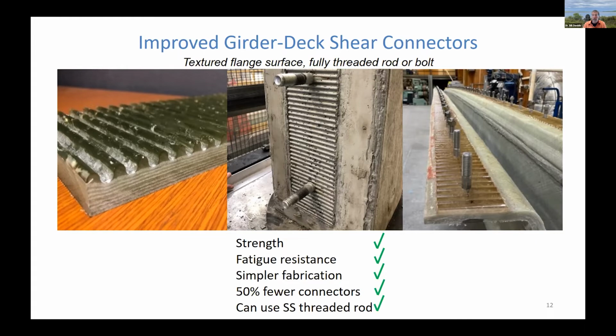And we can also use now, we proved that we can use a stainless steel threaded rod for that connection. So we don't have to worry about keeping threads out of the shear plane. We don't need to worry about using a high fatigue resistance material. We can go with stainless steel. It's 100% corrosion free. Much simpler to fabricate because not only do you have half as many holes, but those holes do not need to be tightly toleranced. They can be cut pretty roughly through there because you're not relying on that bolt bearing on those holes. Those bolts are doing nothing but keeping those two deformed surfaces together.